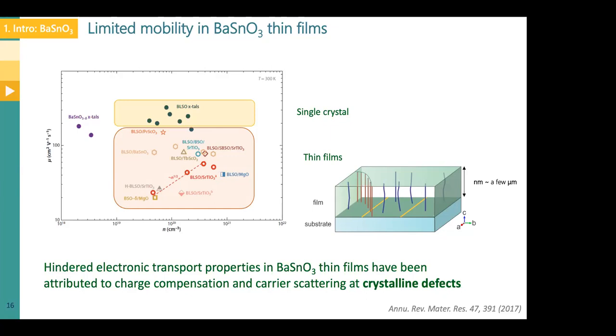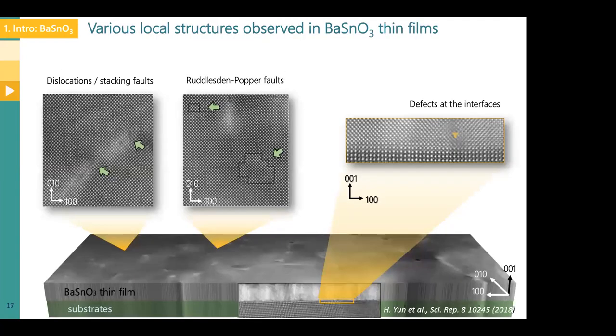And these crystals were grown using molecular beam epitaxy, so they are relatively thin and well controlled. Here's actually an image of that. At the bottom, I showed you how they look: a thin layer sitting on a substrate. And if I look along the plane, you can see these three images. Every white dot you see is a single atom. So now we're talking atomic resolution images.